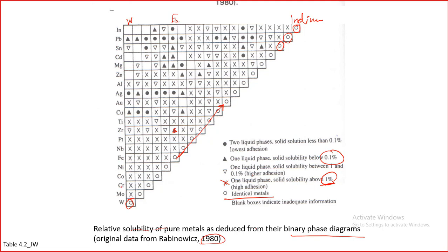Of course, here we have pure metals, and in industrial applications we don't use pure metals, but this gives us some indication, some good rule, that if the solubility is high between two metals, then we should not use them. This is the best: two liquid phases, solid solution less than 0.1%, lowest adhesion. So this is a good pair.